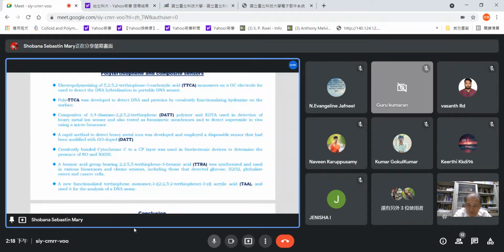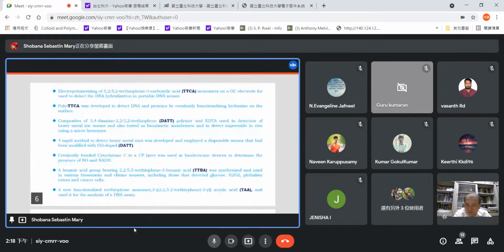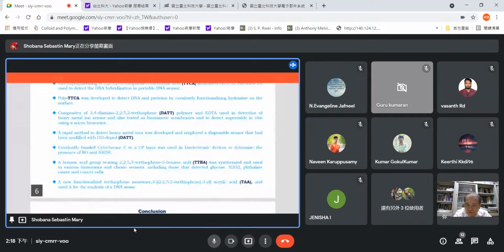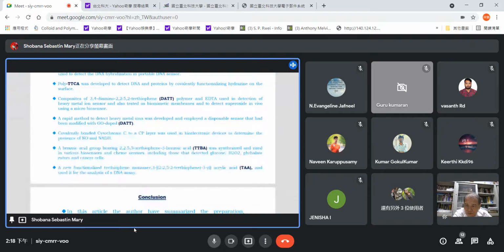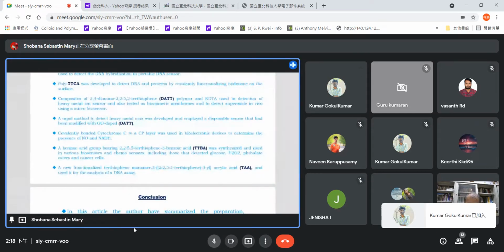in vivo using a microbiosensor. So the DATT was also used to detect heavy metal ions, and was developed and employed as a disposable sensor that had been modified with the doped composites. Cytochrome C covalently bonded to a conductive polymer layer was used in bioelectronic devices to determine the presence of nitric oxide and NADH.